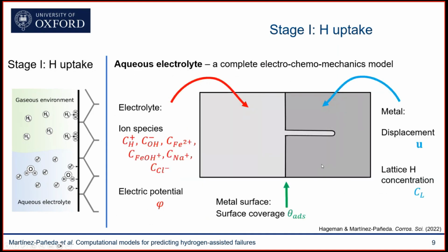So this is what the finite element model looks like. You may have an electrolyte domain, which has as many ionic species as needed, and then you have an electric potential as well. Then you have a metal domain, which might contain a crack or the type of defect where you're solving your mechanical problem. And then you're also solving for the uptake and transport of hydrogen. And then you have an interface between the two where you're solving for the hydrogen surface coverage.